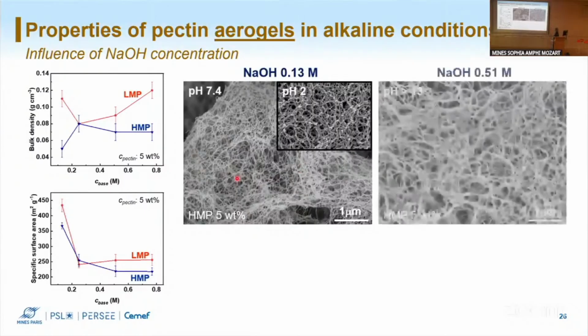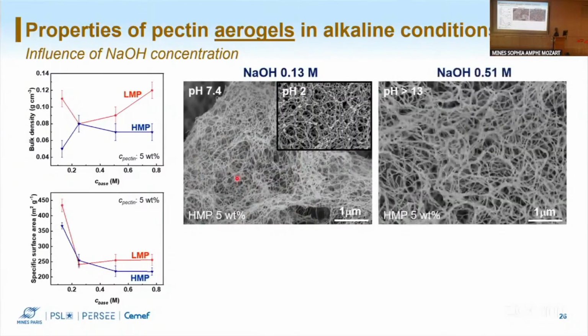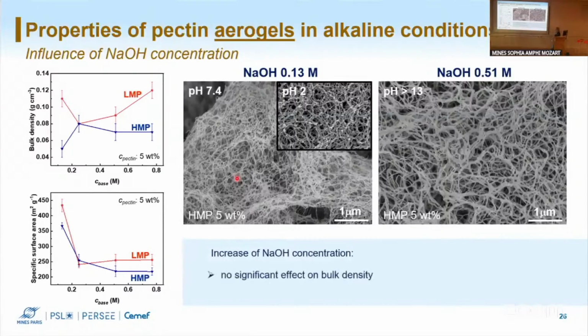But then when we go to higher pH, more base in our system, we see that the structure changes. We have thicker fibrils in our network, and the pores start to be bigger. So for the aerogel materials dried with supercritical drying, when we increased the concentration of base, we didn't have a real effect on bulk density, but then we had a huge decrease of specific surface area, as we can see also from the structure.